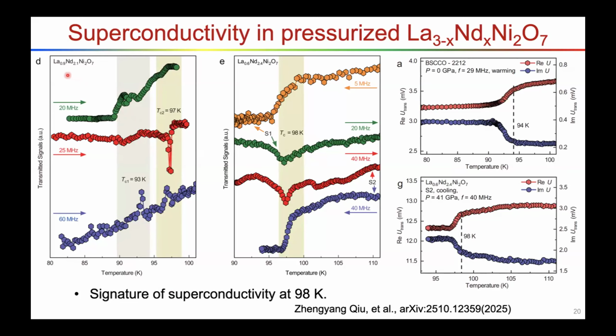for the measurements on our sample, this is a 70% neodymium doping. The TC is at 97 Kelvin. For 80% doping, the onset TC is at 98 Kelvin. As a comparison to the cuprates, this BSCCO has a transition temperature of 94 Kelvin, and here's the analytical plot for the measurements. The transition temperature for the neodymium doped nickelate is at 98 Kelvin. But this temperature is higher than the transport measurements. That means the sample is not homogeneous, and some part of the sample has higher transition temperatures, and the maximum transition temperature is close to 100 Kelvin.